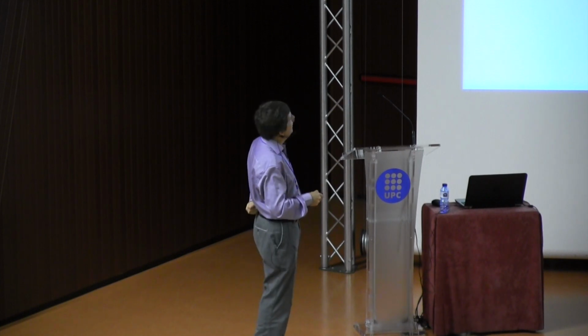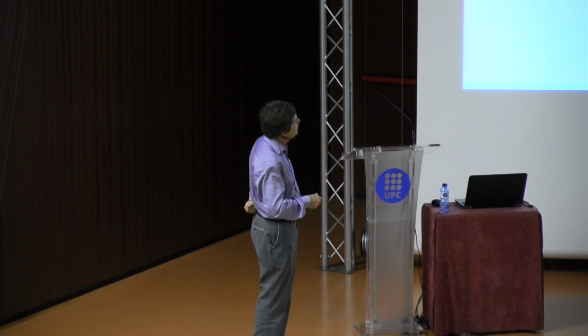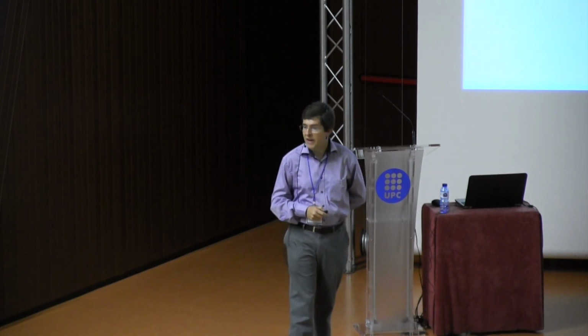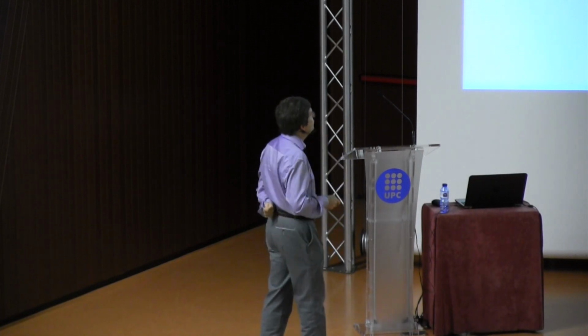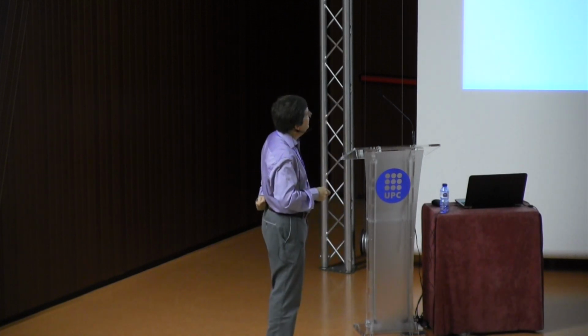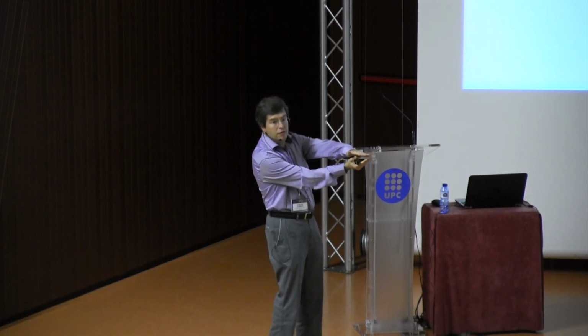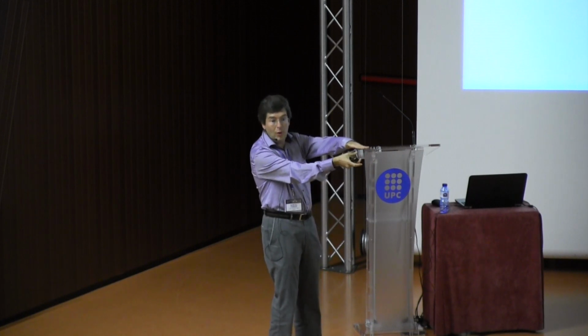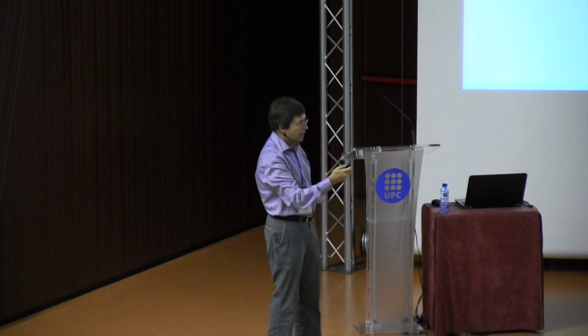I will consider that the strain rate can be split into elastic contribution, crystal plasticity, standard ones, but also damage strain. What do I call damage strain? Simply the possibility of opening strain, like this, along a plane with normal n here, meaning that you have some cracking and you have some volume changes because there will be some cracks inside which opens here.